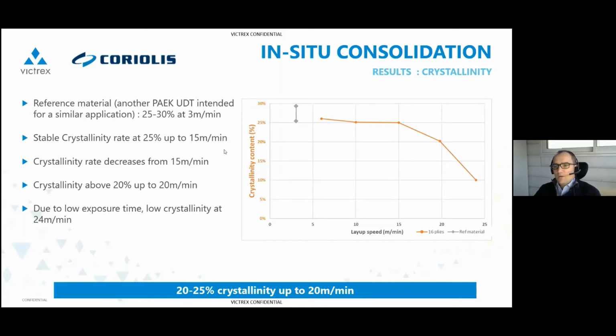So that's maybe why the crystallinity decreases. That means somewhere the quality of the laminate is getting worse when you go faster. But we've been able to achieve 25% crystallinity at 15 meters per minute, which was already a positive result, because we were in this range at more or less 3 meters per minute. So we've been able to increase the speed by 5, and we are more or less in the same range. So, a positive result in terms of crystallinity.